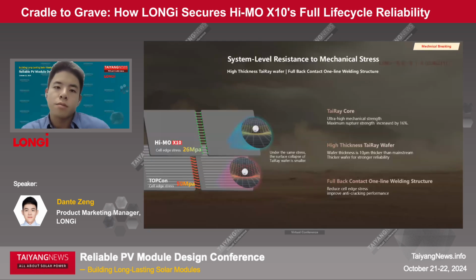And for the last part, it's about mechanical breaking. When the breaking happens, it's not very easy to observe because the hidden crack is not that big. You can only see the crack by putting the module under the EL test machine, not with your own eyesight. But the hidden crack will lead to a lot of things. It will lead to hotspots, and will lead to degradation. It's a minor, small damage, but small damage will lead to huge loss.